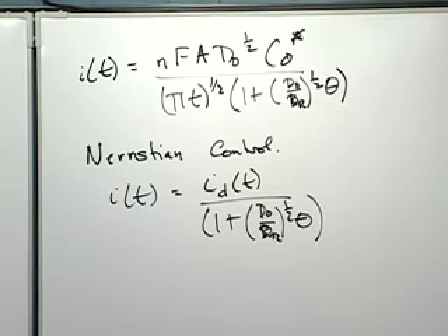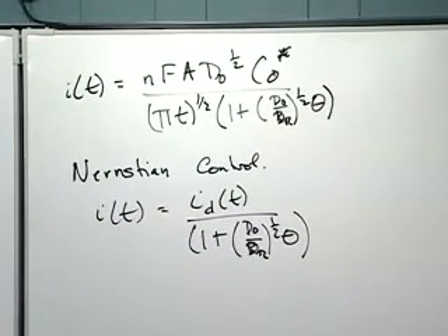Okay, before we consider other cases, so we've now considered 2 important cases that we're going to run into. Let me point out from a practical point of view some of the pluses and minuses of this. Once again, assuming I know what the redox potential of the system is and whatnot, and how much material I've put in, then I can use this to calculate a diffusion coefficient. It's probably one of the better ways of getting a diffusion coefficient for a system. And once again, if I wanted to, I could use it to get at the area, all other things being equal, and assuming the area is not for a porous electrode, but one that's going to respond to this time scale. In general, I would not do it this way, because I can get it from the Cottrell equation with a big step and not have to introduce these other terms over here.